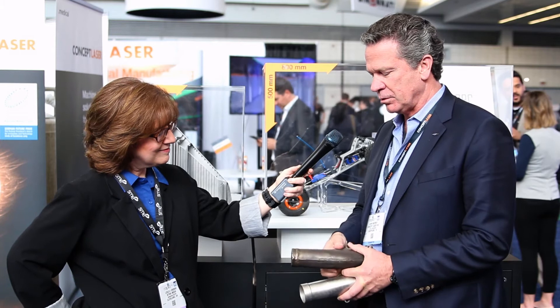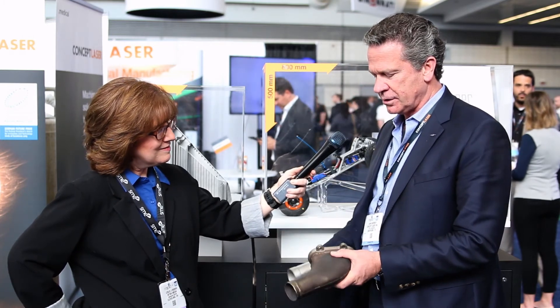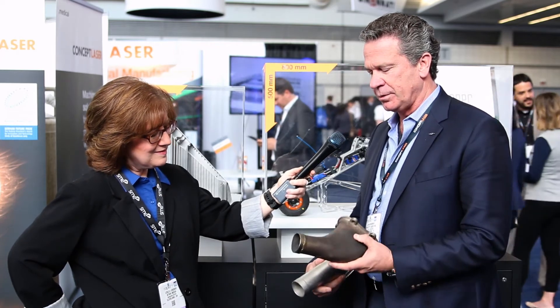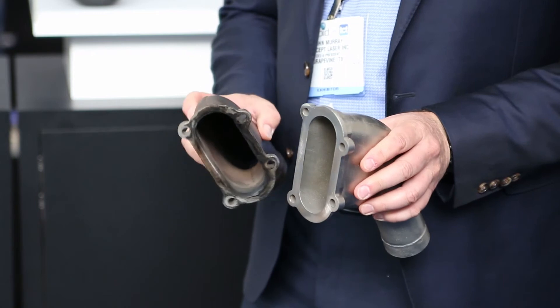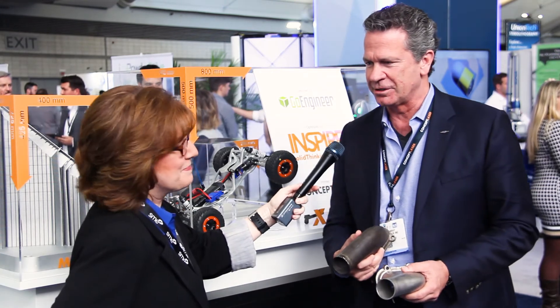So we looked at these exhaust stacks. This is the original from the 1940s — it consists of four pieces: a base, two formed shells, and a ring at the top, with 34 inches of weld seam on this component. With PADT in Arizona, they did a blue light scan, and then we printed it on the M2 — two at a time — and installed them on Rob's P-51 and ran them in stainless steel, which is the original alloy called out in the 1940s drawings. It was great to reach back into history, and again, it's touching every aspect of our lives.